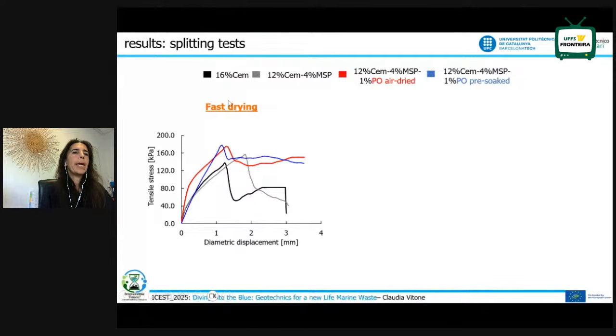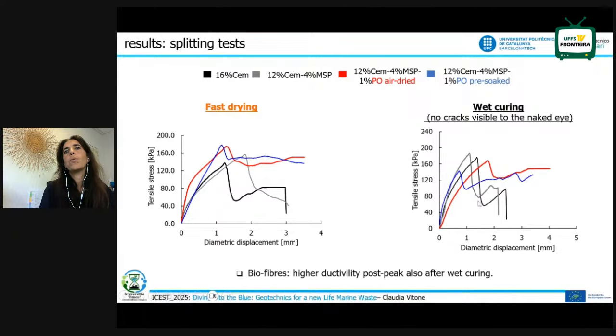If we compare the tensile test results after fast drying with those after wet curing, where we couldn't see any visible crack to the naked eye, we have quite similar results. And what is very interesting is that also under tension, we have very huge post-peak ductility when we add fibers, here in red and in blue.